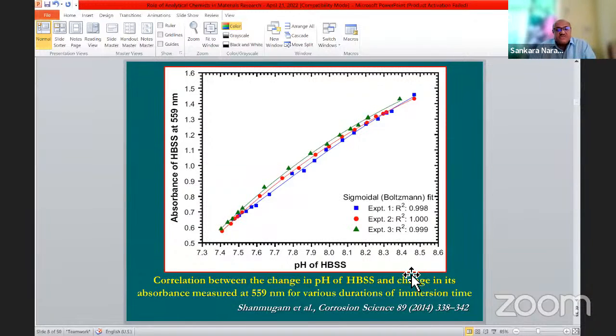But absorbance measurements are more accurate and reliable. Because with pH variation, sometimes if you don't properly calibrate the pH meter, or if you don't keep the glass electrode in acidic medium during storage, it might not sense properly. So those problems may be there. Compared to pH measurement, absorbance measurements are more sensitive. Even if there is a slight change in the color of the solution, you are able to measure the absorbance of the solution. So that is the advantage of measuring the absorbance of the solution over measuring the pH of the solution.